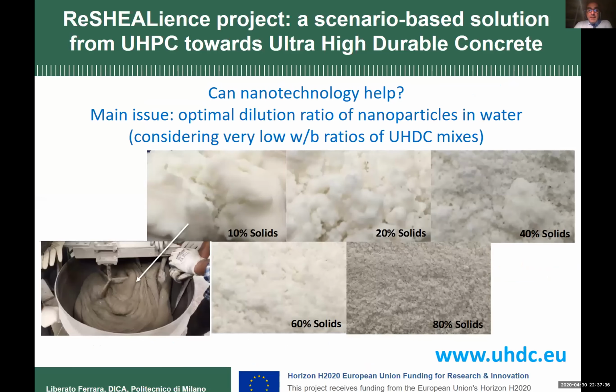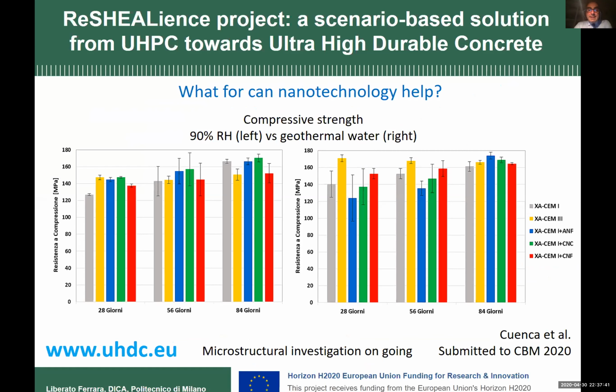So we said, okay, let's see how this nano addition works. We tested compressive strength first, curing the specimens in a climate room or under the geothermal water we kept from the plant where we were going to build the pilot. We were a little disappointed in the beginning, because the results showed the effect of the nanofibers was not so good, especially looking at the long term — the reference mix is the gray column.